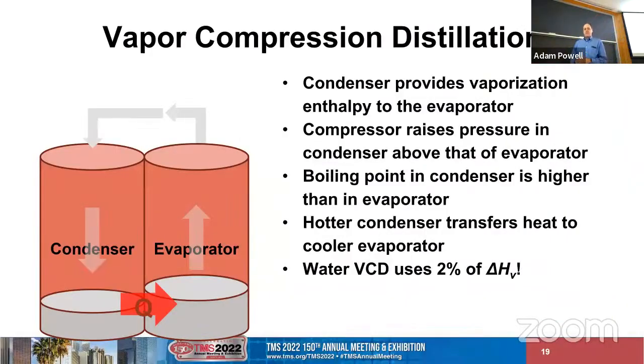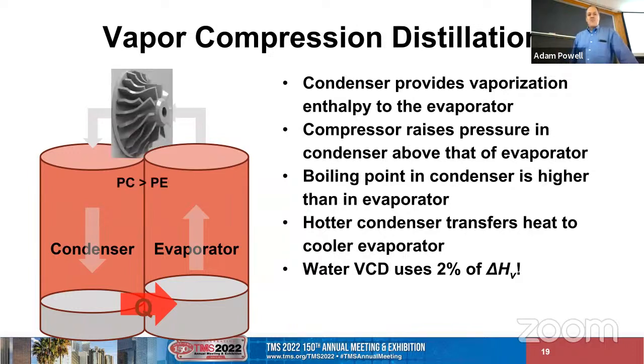So I'll talk a little bit about compression distillation. The idea is that the energy of condensation provides the energy needed to evaporate your material. And this sounds like a perpetual motion machine. That's because, as described here, it is. You need a compressor to compress the vapor so that the pressure in the condenser is higher than that in the evaporator. Therefore, the boiling point in the condenser is higher than the evaporator, and the hotter condenser transfers heat to the cooler evaporator. So David Dussault was able to demonstrate this for a water system with input energy that's only 2% of the vaporization enthalpy of water. So the other 98% of the energy comes from the condenser. So a really impressive system. He said that was the motivation, the inspiration for doing this with magnesium.